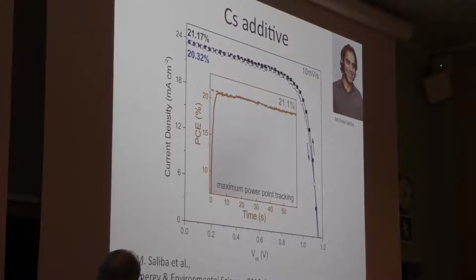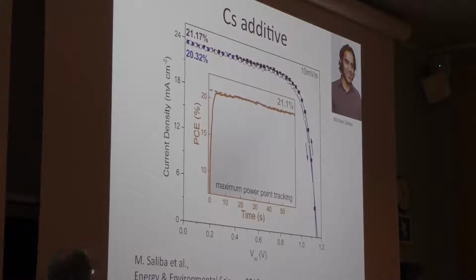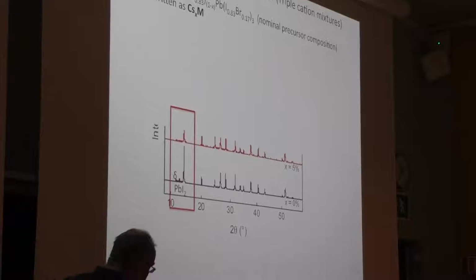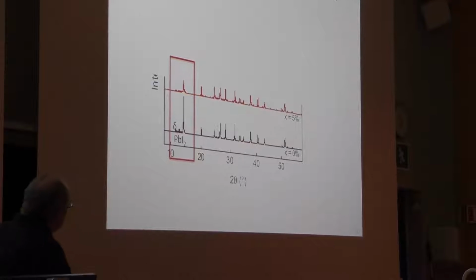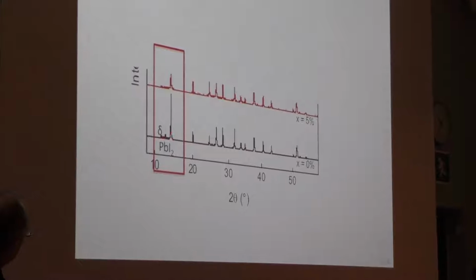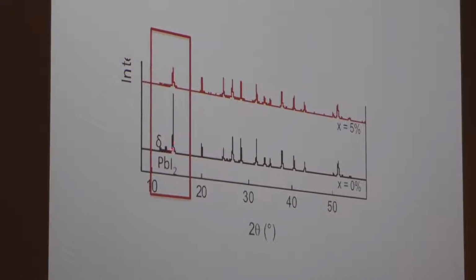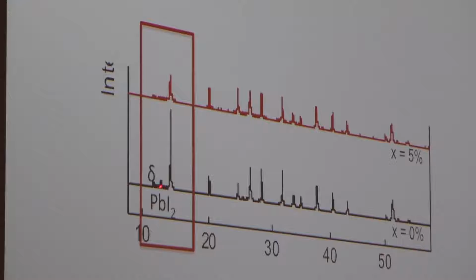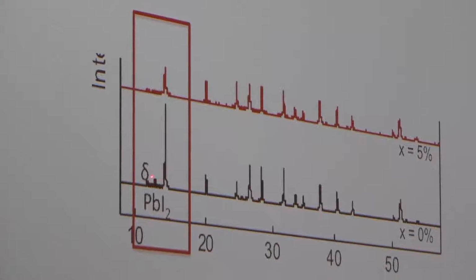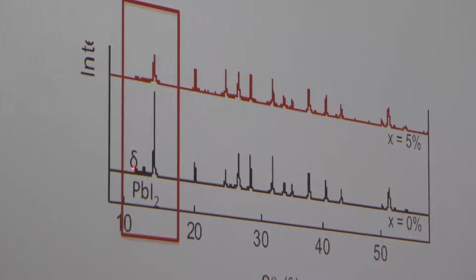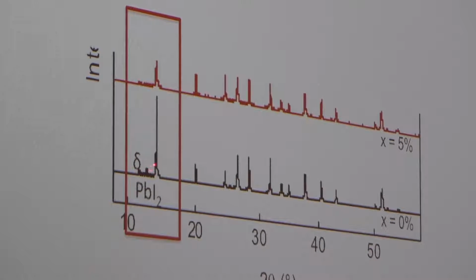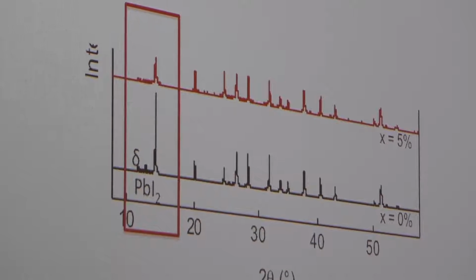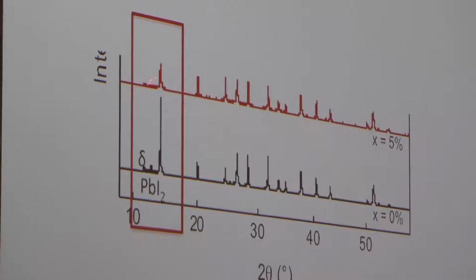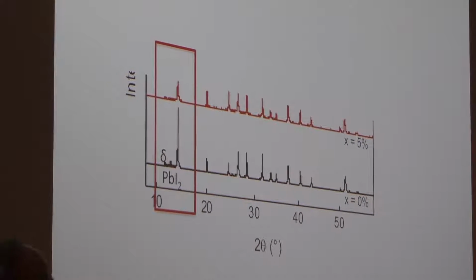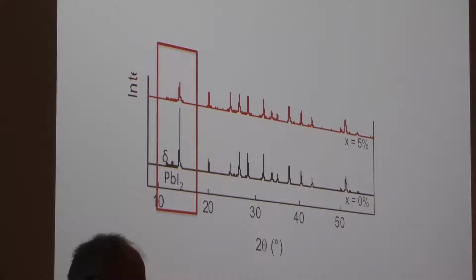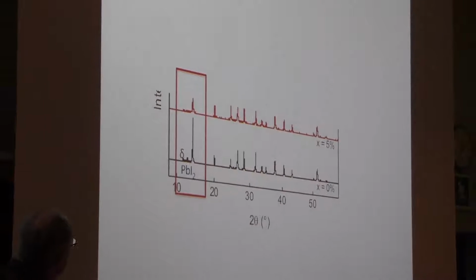Nice IV curves, 21% efficiency, but what is interesting here to see is if we do without the cesium, we do have some impurities in the perovskite film. This is XRD, this is the perovskite peak, this is lead iodide, and this is a yellow delta phase which is not photoactive. So these are 2 impurities coming without the cesium, and with the cesium we really decrease these 2 impurities. So we form even larger, higher quality crystals with this mixed system.